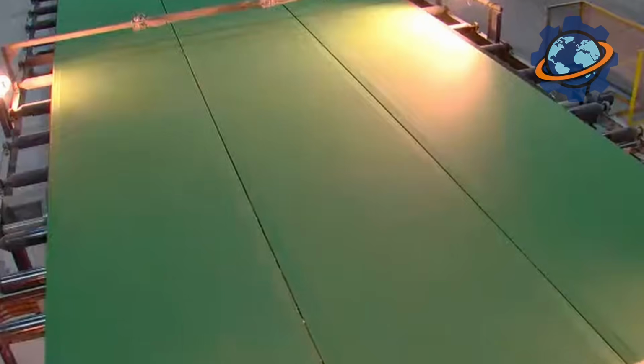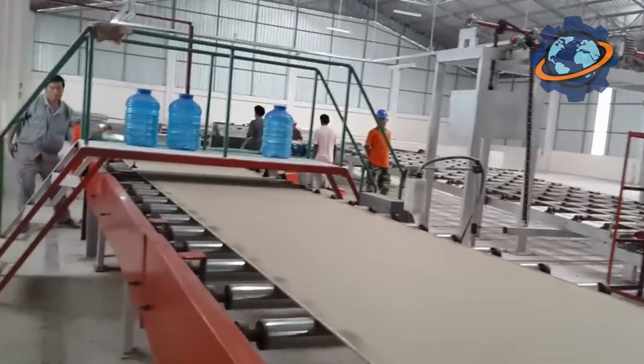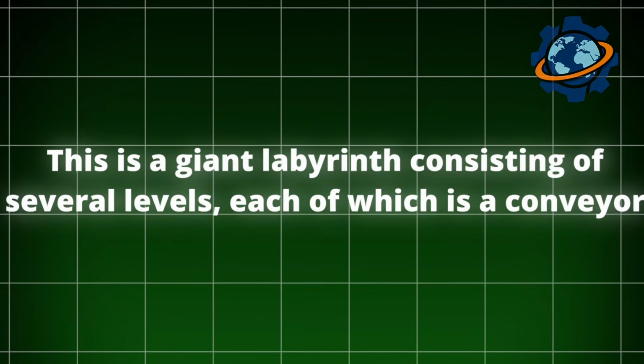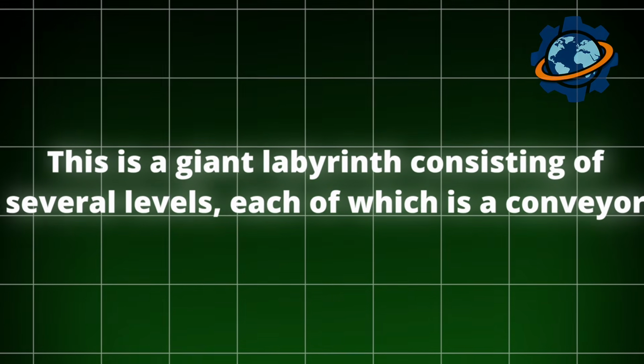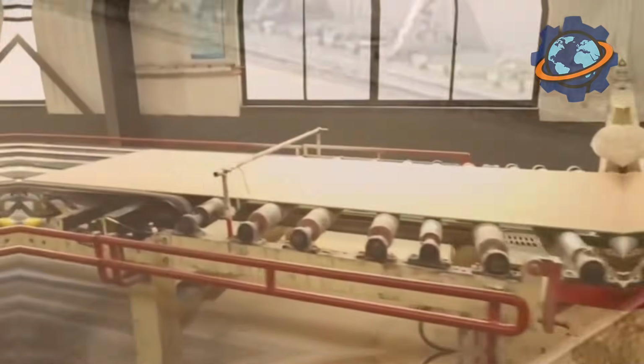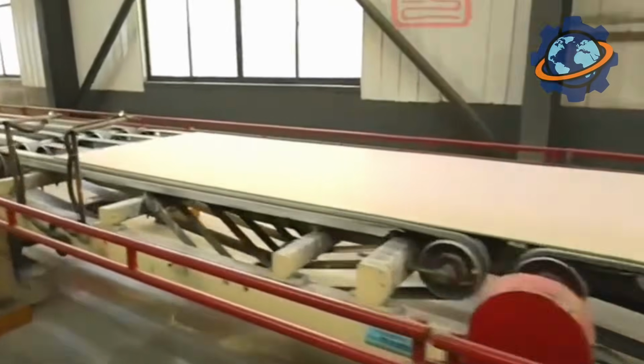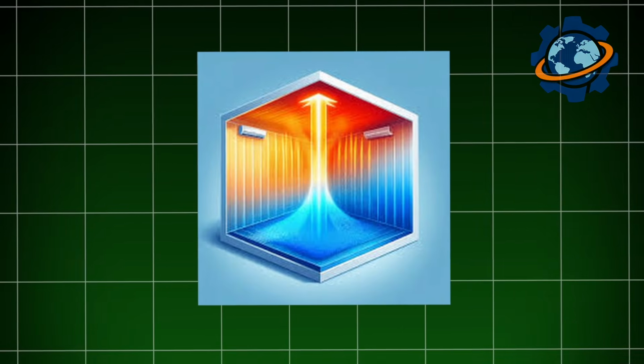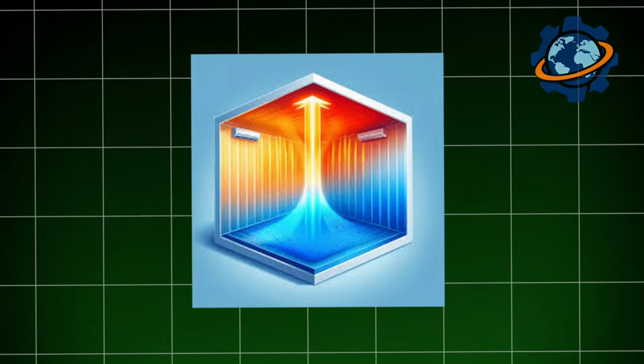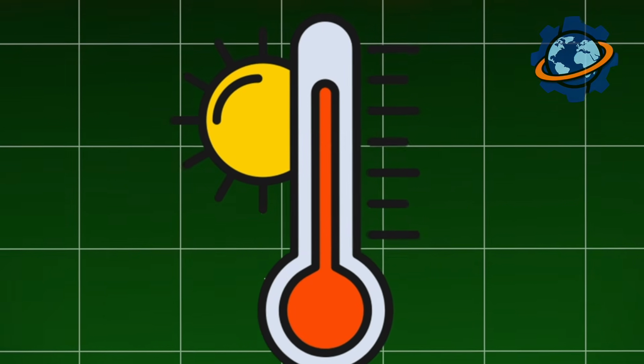Therefore, a special device flips the sheets and feeds them into the most large-scale structure in the factory, a multi-level drying kiln. This is a giant labyrinth consisting of several levels, each of which is a conveyor. The drywall sheets slowly move along these levels back and forth, traveling a path of several hundred feet inside this huge furnace. Hot air circulating inside gently evaporates the excess moisture from them. The temperature here is controlled very carefully. Only the free water needs to be removed without damaging the crystal structure of the gypsum itself. This process can take about an hour. At the exit of the dryer, the product we are familiar with appears, a perfectly dry, light and strong sheet of drywall. But this is not the end.